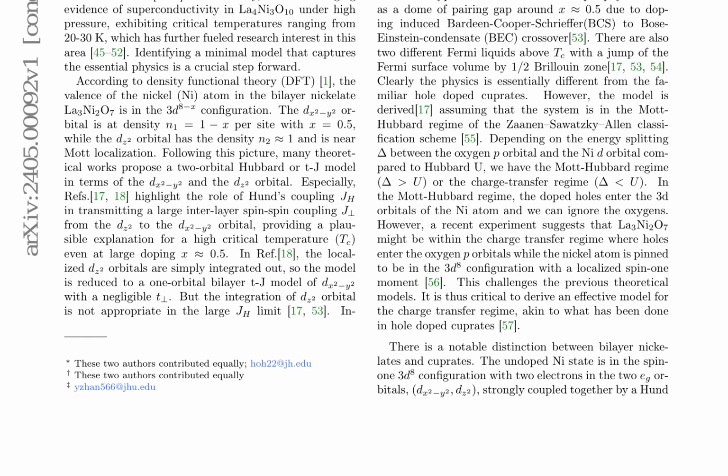with power law interlayer pairing correlations. The pairing gap decreases with increasing t-perpendicular but remains robust at small values of t-perpendicular. The doping dependence of the pairing gap is also explored, showing a dome centered near x equals 0.4 to 0.5 in the presence of a finite interlayer repulsive interaction. This suggests that the two-orbital bilayer t-J model could be relevant for understanding high-temperature superconductivity observed in bilayer nickelates.